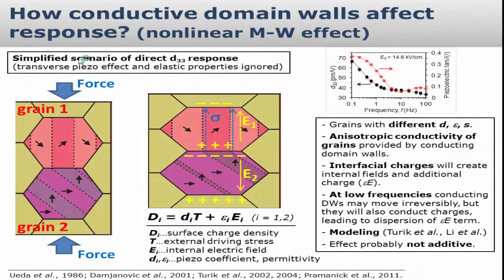So we think that this conductivity of the domain wall, which was first discovered in thin films and looks like it is also present in bulk ceramics, may have a large influence on the electromechanical behavior, which I think would be important also for other BiFeO-based materials in the future. This is the mechanism, called the nonlinear Maxwell-Wagner effect. I think Dragan will explain this in much more detail in the tutorial.